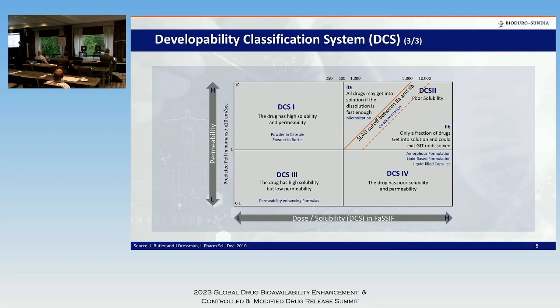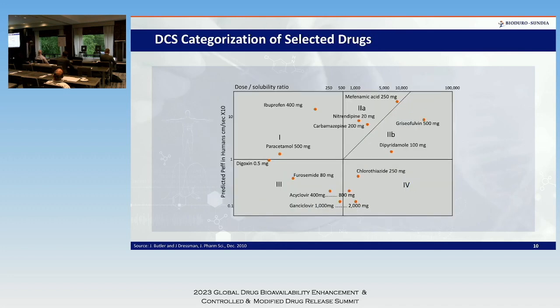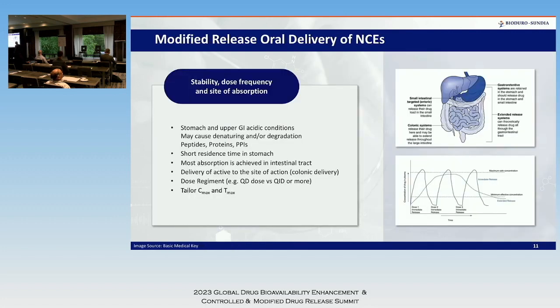Amorphous solid dispersion is going to work only if you have a saturation solubility issue. Lipid-based formulations and so on can be utilized here. Micronization and nanosuspensions are going to work only if you have a dissolution rate issue and not a saturation solubility issue with regards to your drug product. And they further showed this using model drugs that are already developed and commercialized.